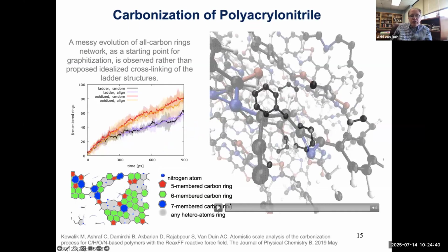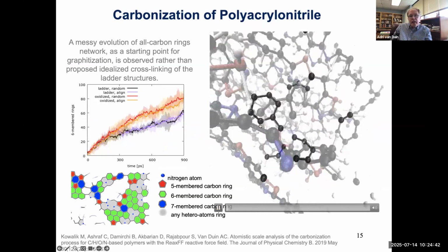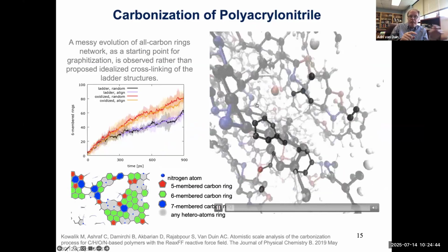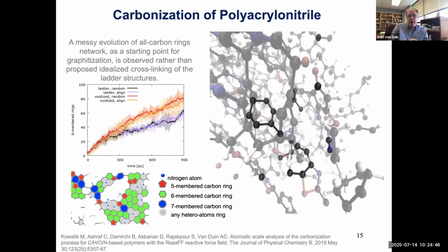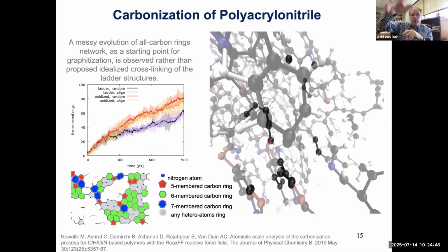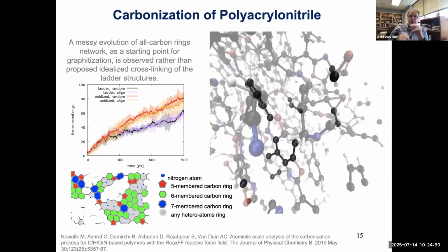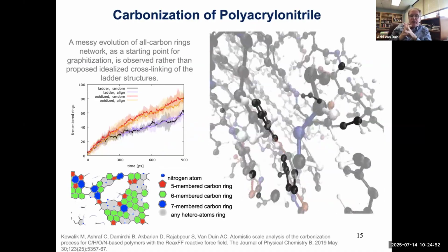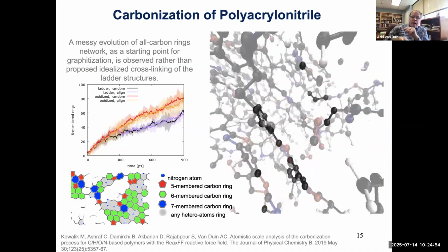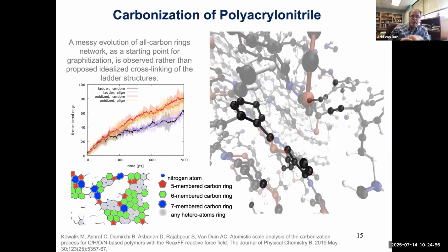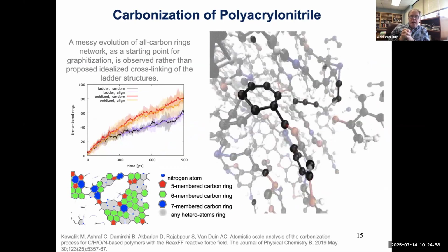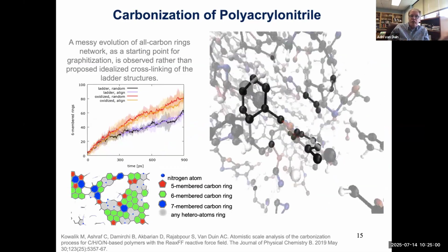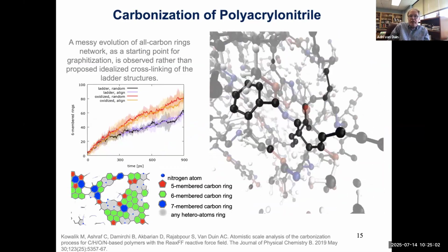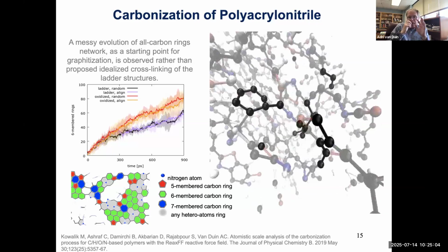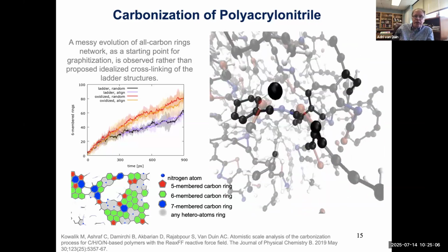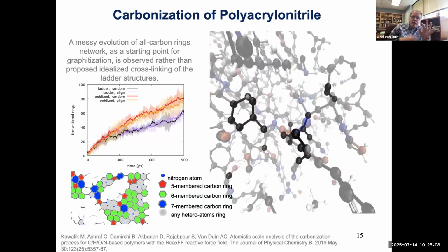And so here you can see a snapshot from a simulation. Look at the black atoms. These are eventually going to grow into a larger graphitic area. The rest of the environment is faded out a little bit, so you can focus on the growth. Every now and then you see a new carbon atom getting added to the material, and eventually they'll start to grow a more interconnected graphitic material. But as you see at this temperature, roughly 2500 Kelvin or so,